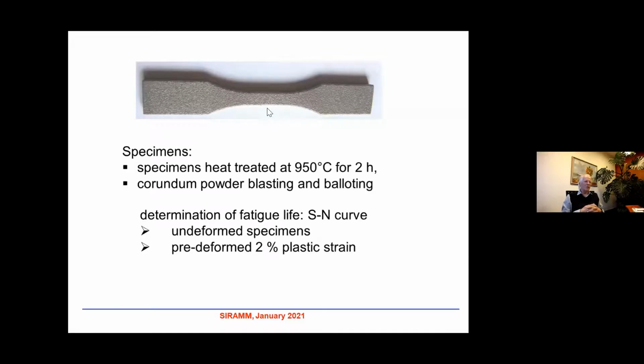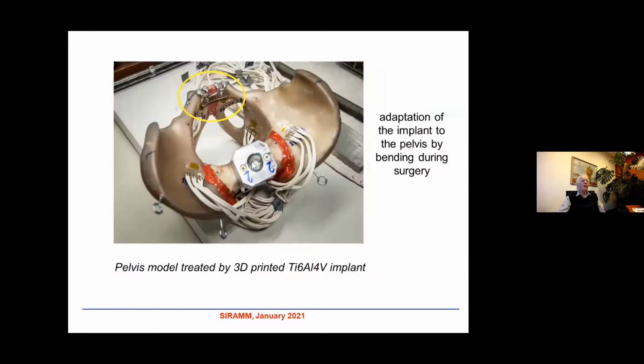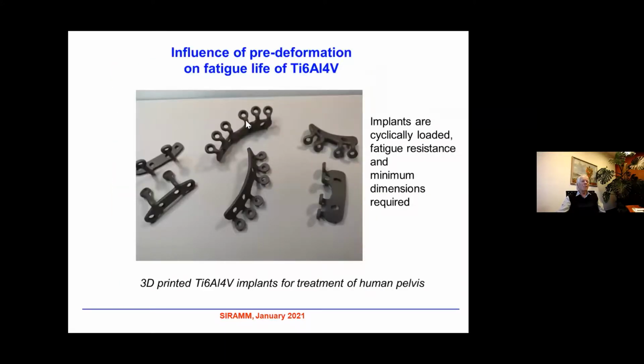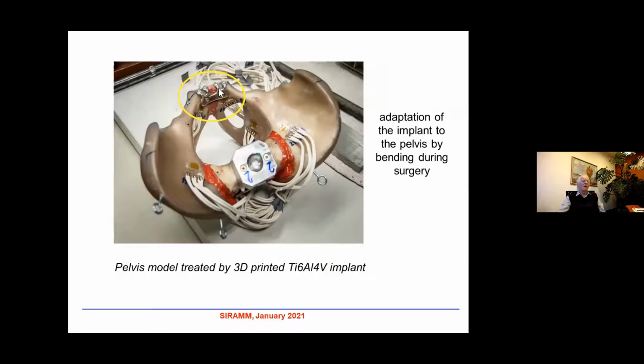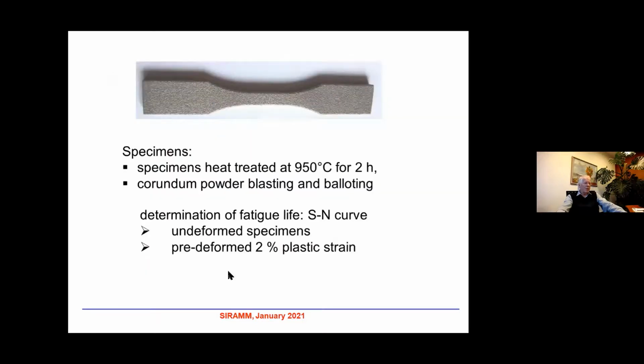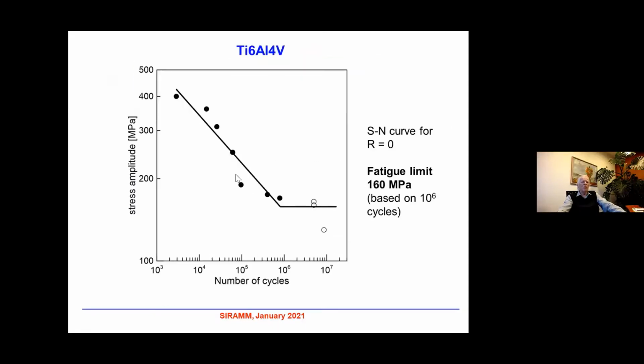And now we wanted to determine the fatigue life curves, S-N curves, for undeformed specimens and pre-deformed specimens. The reason was simple. If you apply this implant to the pelvis, in the procedure, it is slightly bent during surgery. These parts are bent. And now there is a question. In the case of conventional steels, it doesn't play a role. How is it in the case of implants which are printed? So we pre-deformed specimens to 2% plastic strain and we formed S-N curves.